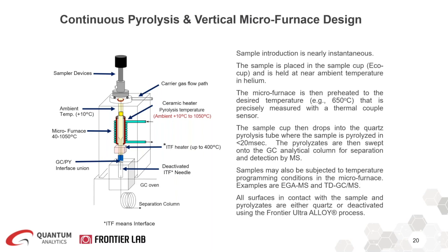The sample cup then drops into the quartz pyrolysis tube where the sample is pyrolyzed in less than 20 milliseconds. The pyrolyzates are then swept onto the GC analytical column for separation and detection by the MS.